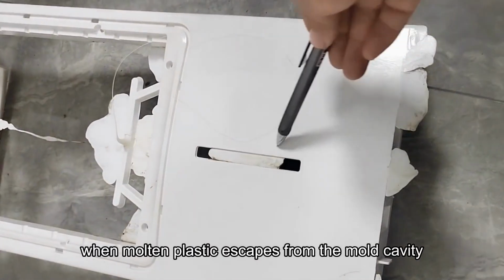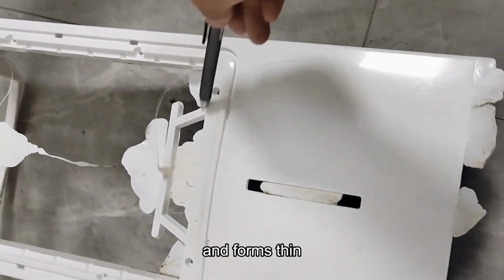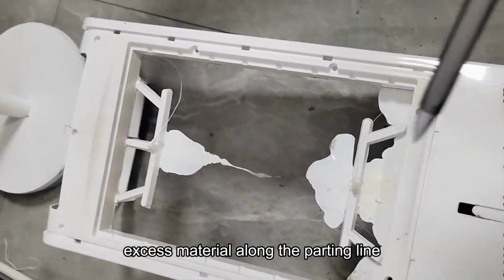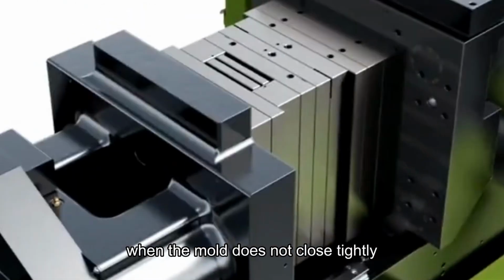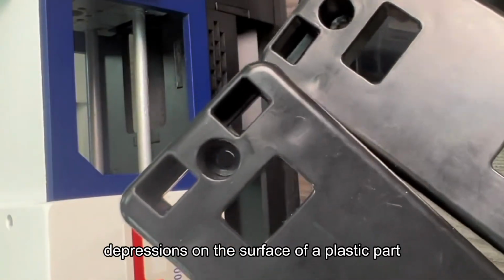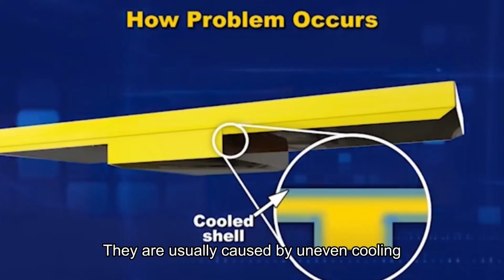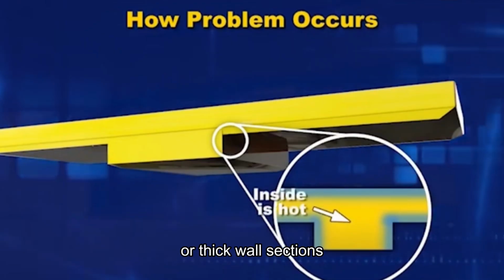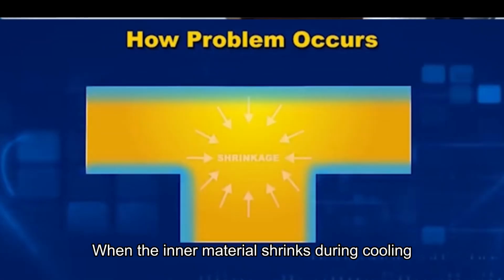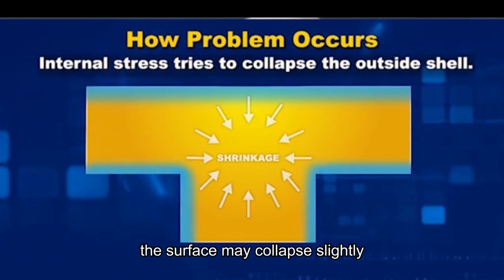Flash occurs when molten plastic escapes from the mold cavity and forms thin excess material along the parting line. This usually happens when the mold does not close tightly, or when the injection pressure is too high. Sink marks appear as small depressions on the surface of a plastic part. They are usually caused by uneven cooling or thick wall sections. When the inner material shrinks during cooling, the surface may collapse slightly.